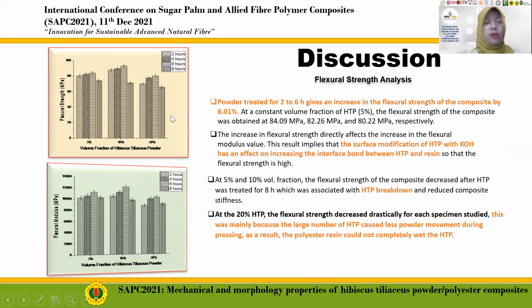Ladies and gentlemen, as you can see in the chart, we know that the powder treated for 2 hours, 4 hours, and 6 hours gives an increase in the flexural strength of the composite by 6%. And then at a constant hibiscus volume fraction of 5%, the flexural strength of the composite was obtained at 84 megapascal, 82 megapascal, and 80 megapascal respectively.